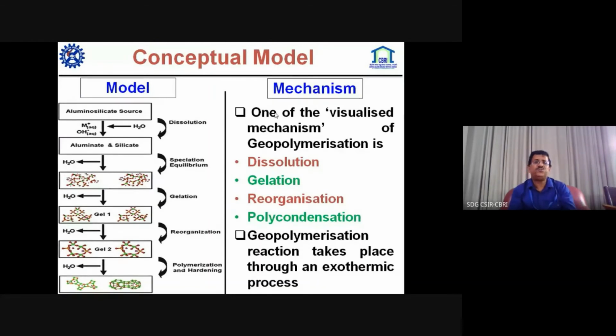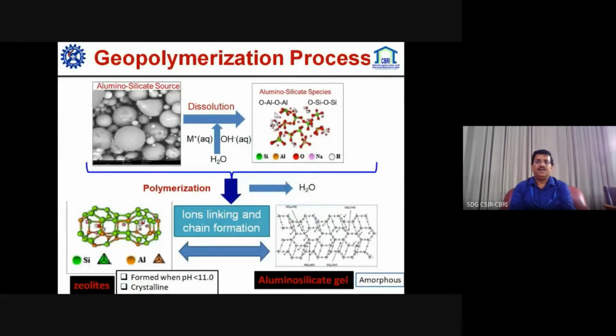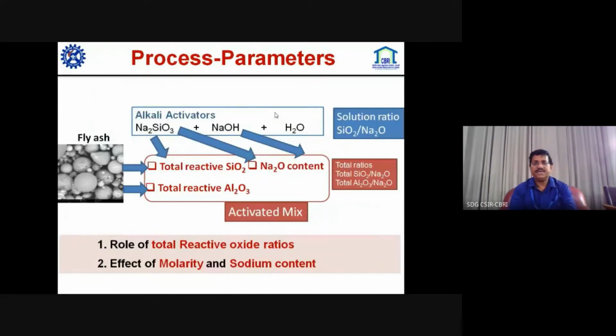And in every reaction, if you look into it, water is coming out from that reaction. So we have to look at how that water should be utilized. These are different processes. It is important that dissolution should be carried out in a very high alkaline atmosphere, with a pH of 12 or more, so that it is converted into amorphous aluminosilicate gel. Otherwise it will be in a crystalline form, and strength and other properties will be lesser compared to the amorphous material. So that is important.